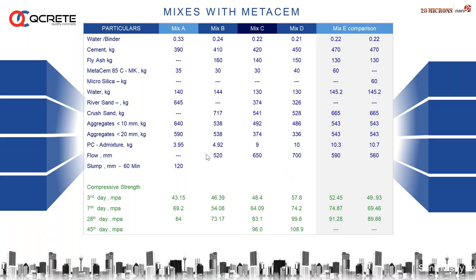So you can see here, these are some of the mixes, named mix A, B, C and D. We conducted this trial at the project site. In the first combination, you can see, it is only 390 kg of cement with only metakaolin added here, and we kept the water cement ratio a little bit on the higher side at 0.33, and we get a result of 28th day is 84 MPa is possible.